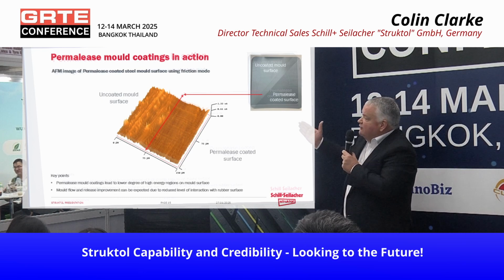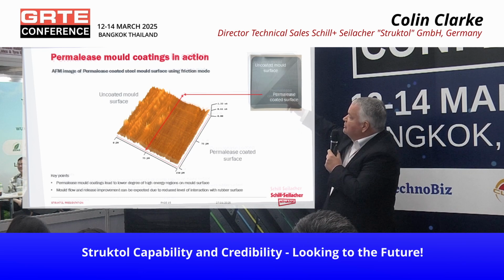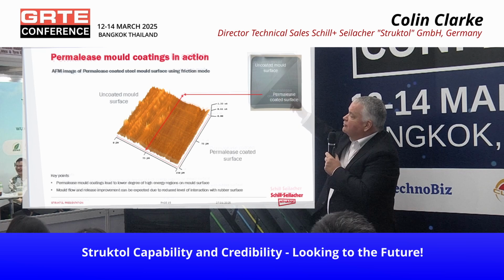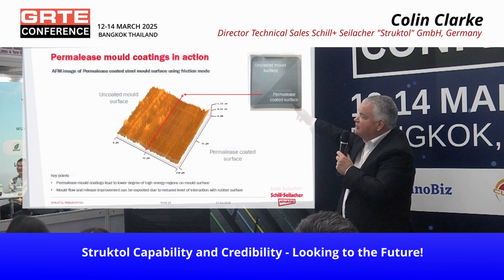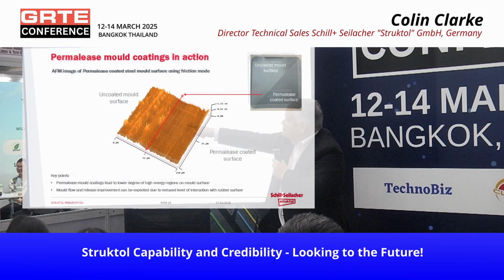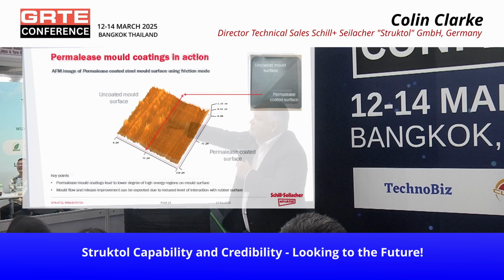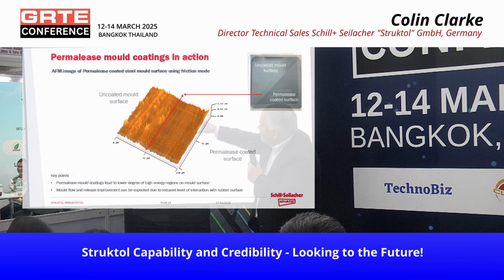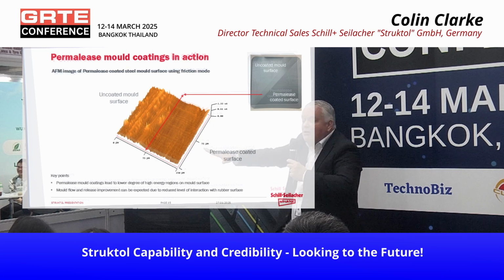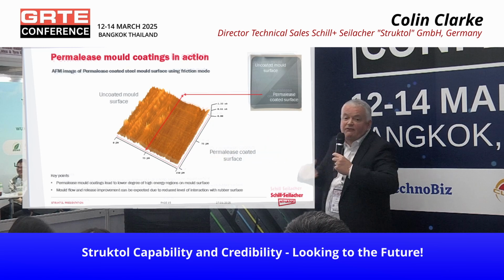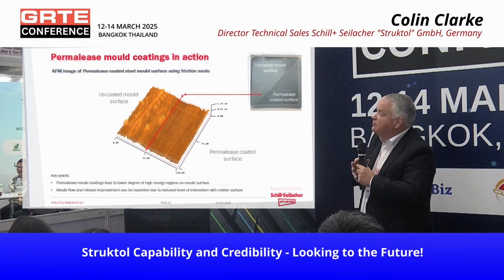We know that because if we coat a mold, uncoated versus coated, and we do an AFM, atomic force microscope, to look at the friction, we can see a very high friction surface, uncoated, because the surface is very irregular. On the coated surface, the energy is much lower, a much more regular surface with a very high slip and release potential.